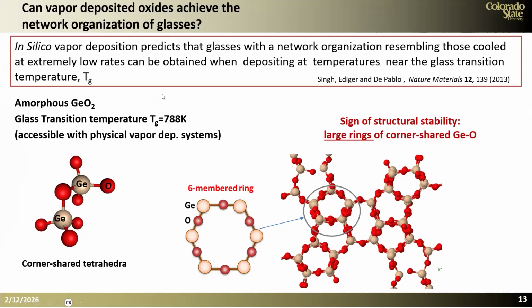So we did some search among all the families of oxides, and we realized that amorphous germania has a glass transition temperature of about 788 Kelvin, which is very accessible with the deposition system. We can heat up the substrate to temperatures. I mean, we did heat up to about 400 C. And so then we said, okay, we're going to deposit the material.